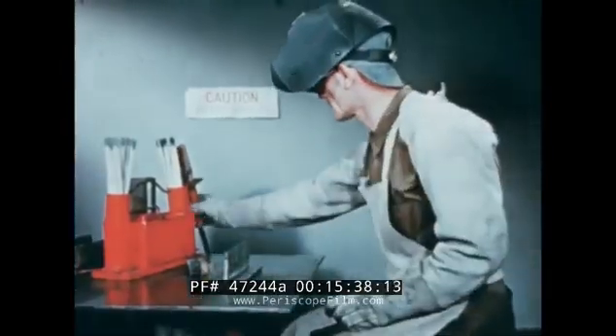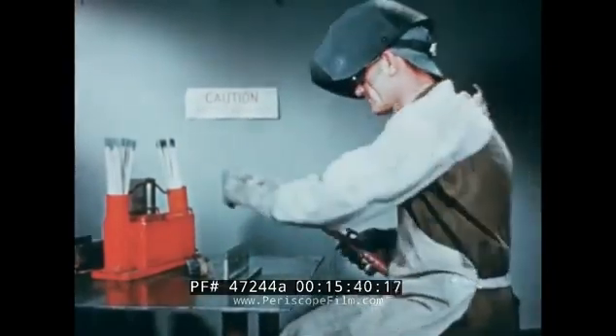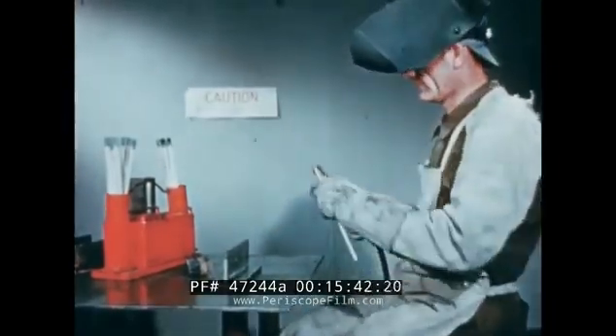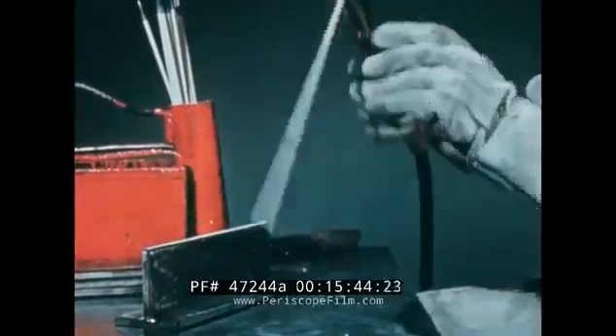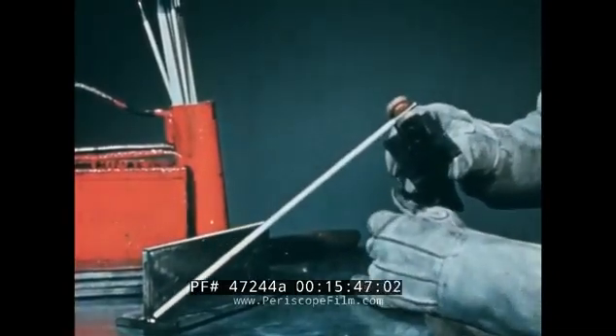Again, we must take electrode diameter and plate thickness into consideration before setting the current. With DC reverse polarity, using a 3/16" all-position electrode, a machine setting of 130 amperes will produce 24 to 26 volts with a correct arc.